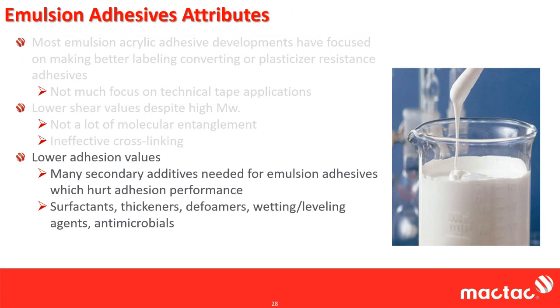One other attribute of adhesives, unfortunately for emulsions, is that we do see lower adhesion values. Again, I focused on the manufacturing of emulsions to kind of explain this. You have to use a lot of secondary additives for emulsion adhesives, and that really hurts their peel performance. The surfactants in there are going to hurt peel performance. The thickeners, you have defoamers, you have wetting and leveling agents. You even have antimicrobials in there to keep down the fungus and mold that will attack an emulsion adhesive.